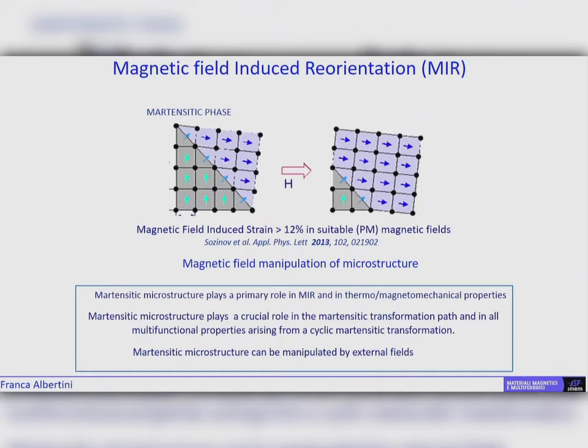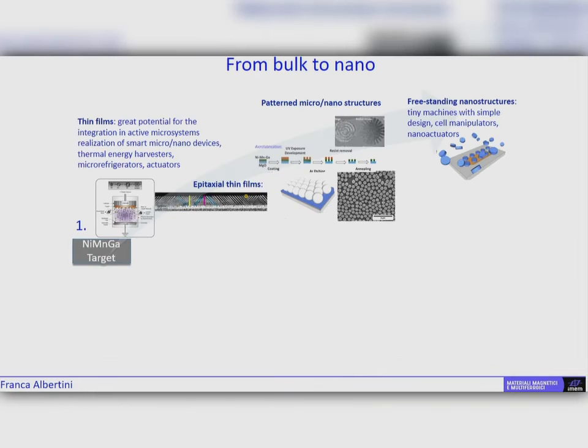suitable fields. So the microstructure plays a primary role in all the thermomagnetomechanical properties, but also it's important for the multifunctional properties arising from the cyclic application of external field, because it influences the martensitic transformation path and the hysteresis. And, okay, this I've already said.